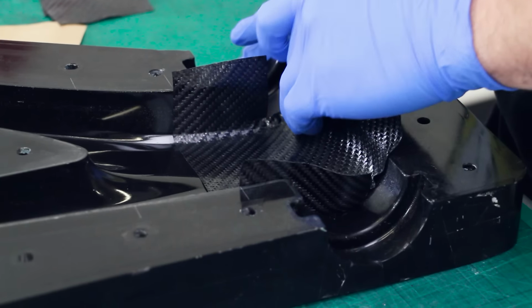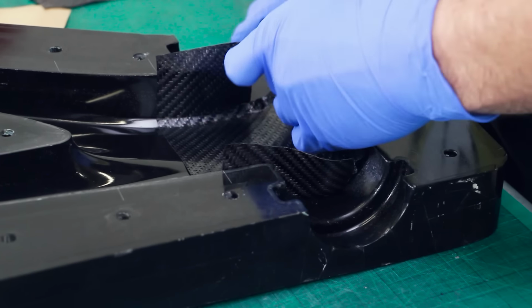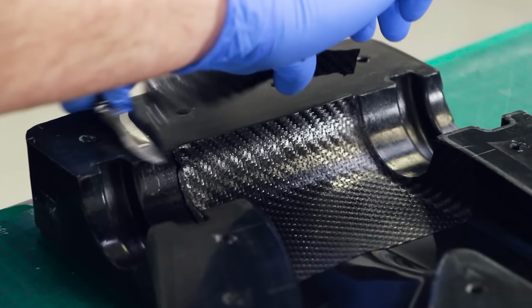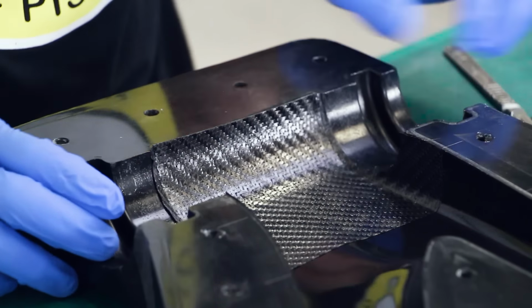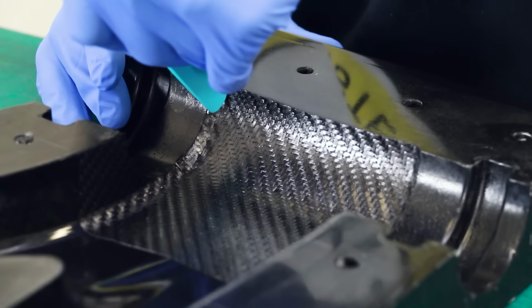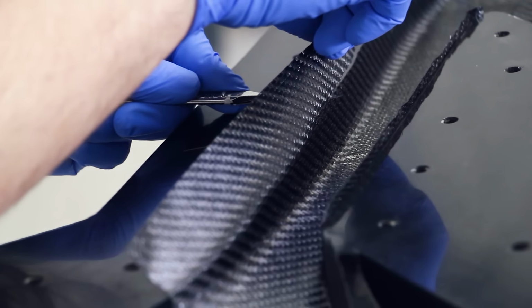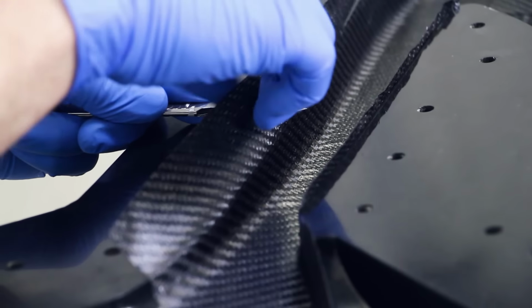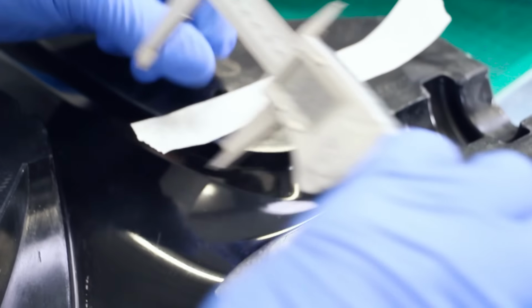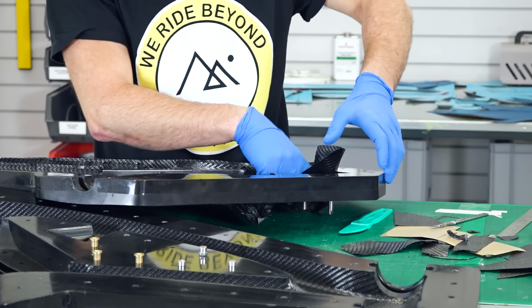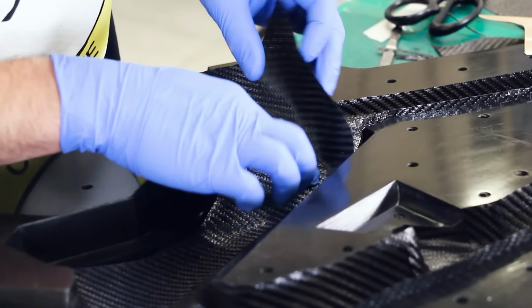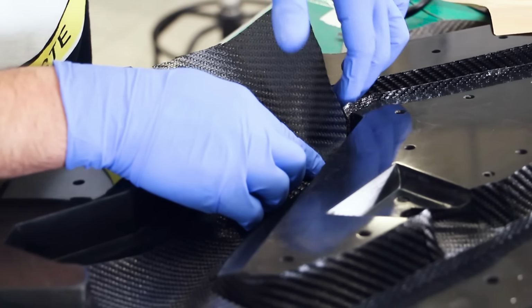The first ply into the mould is the layer that will be visible on the outside of the part. So when you are looking for a really good cosmetic finish, extra care should be taken with this ply to ensure that all of the weave is perfectly oriented, laminated and aligned. One side of the frame is trimmed down to the mould flange and the other will be left protruding to start the laps that join the frame halves.